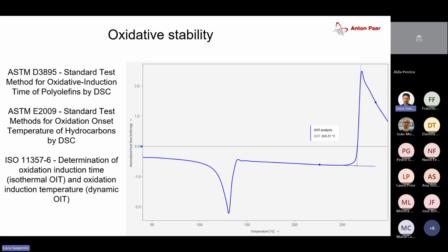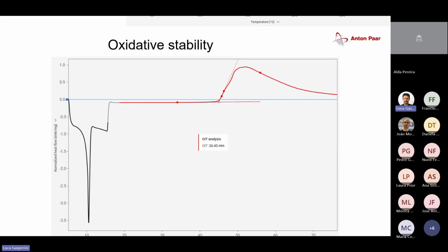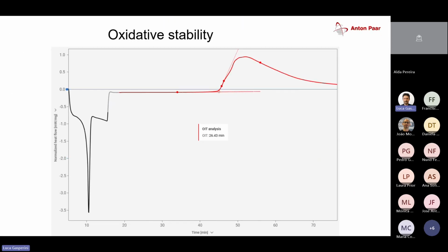That's very nice. We can also have a look at the other approach, which is called OIT, oxidation induction time, which is performed slightly differently. Because first we heat the sample dynamically to a given temperature of the test, in this case 230 degrees, in an inert atmosphere of nitrogen. So that's the black part of the DSC curve, and we actually see the material melting there as well, so an endothermic peak.